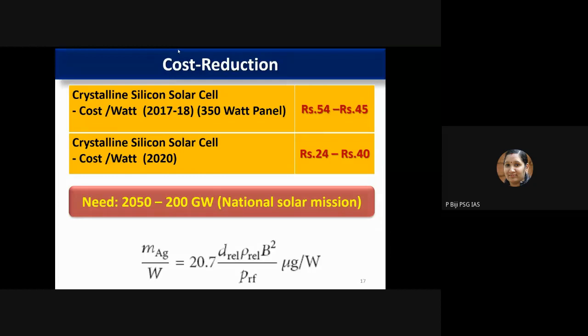So what this means is that although not many advances have happened in the silicon solar cell structure, or the design of the solar cell has not changed, many advances have happened in terms of cost reduction. Typically the major cost during cell processing comes from the metallization. Almost 40% of the cell processing cost is contributed by the expensive silver paste used for the metallization process. So if you can somehow reduce the quantity of metal paste used for metallization, you can considerably reduce the price of the solar cell. That's the beauty of this particular area.